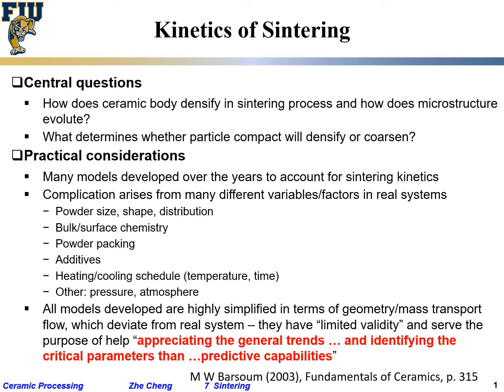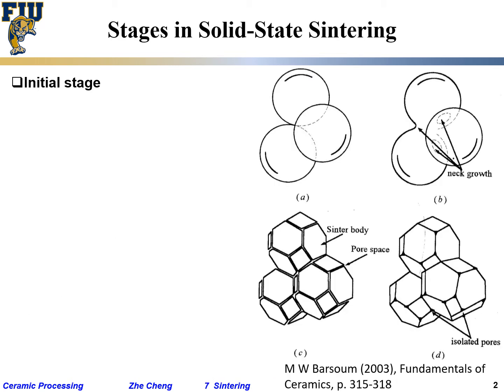The models give you a trend, but quite often beyond a certain point the trend reverses. For sintering, you don't sinter at too low a temperature because you never achieve full density, but you also don't sinter at too high a temperature because you can densify too quickly and towards the end you still do not achieve full density.